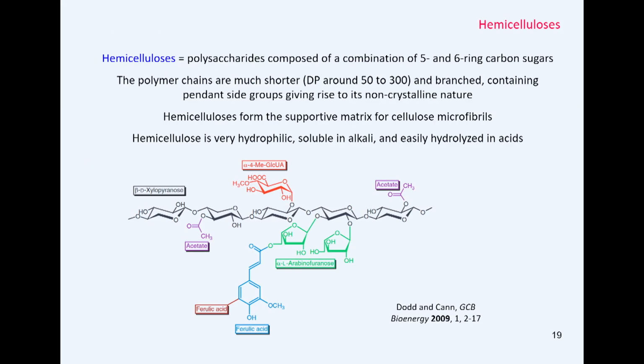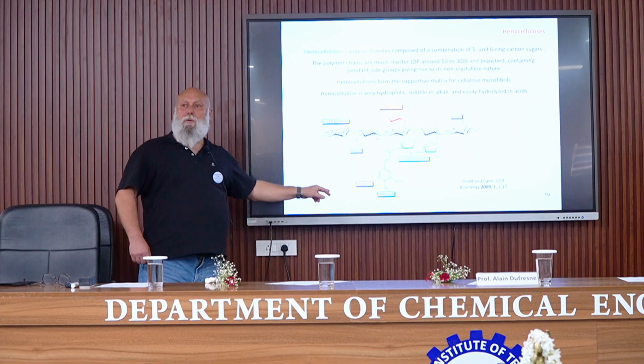So now hemicellulose, which is another component of natural fiber. It's a polysaccharide which is composed of a combination of 5 and 6 ring carbon sugars. The degree of polymerization is much lower compared to cellulose, from 50 to 300. This macromolecule is branched.